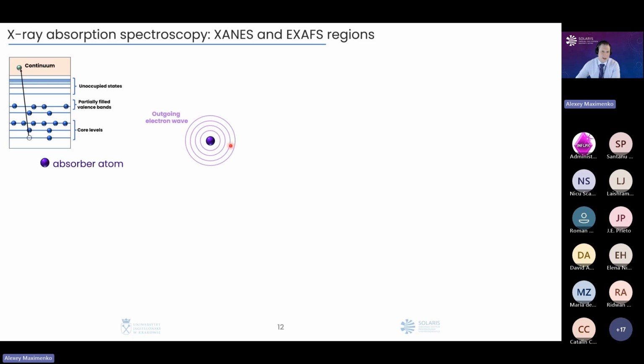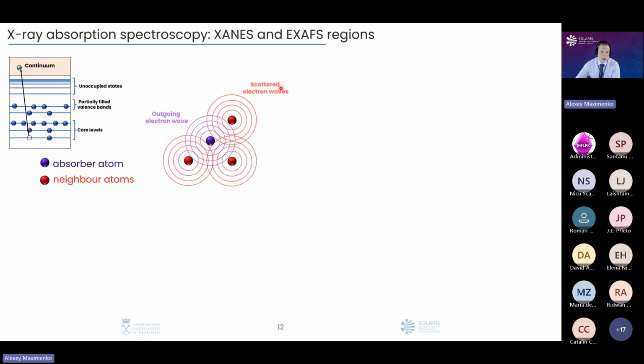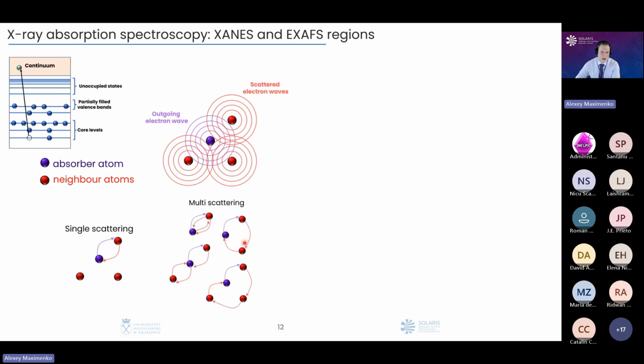And here we could talk about this photoelectron as an electron wave. It is going from our absorbing atom, and as we know, in the material we have neighbor atoms. This electron wave could be scattered from these neighboring atoms, and that's how the scattered electron wave appears. This electron wave could come back to our absorbing atom, or it can also travel somewhere else, scattered from other neighboring atoms, and then we will have a more complicated trip which this scattered electron wave made before it reaches the absorbing atom.